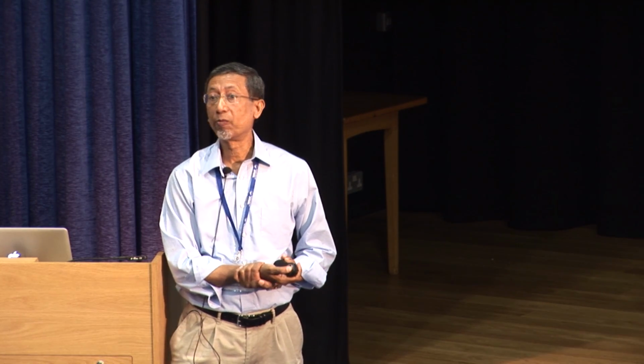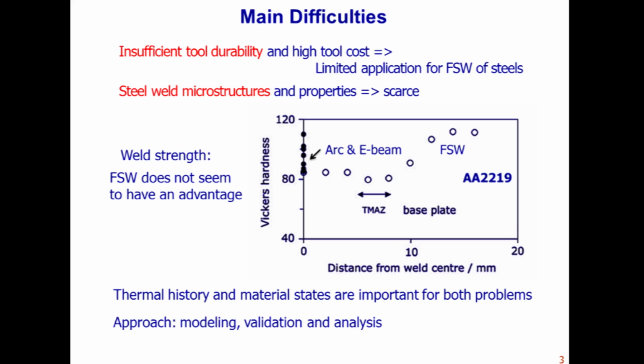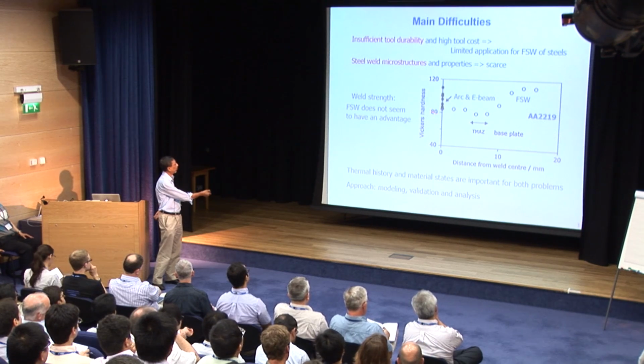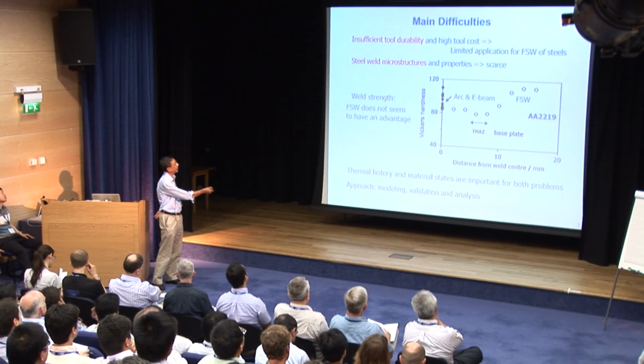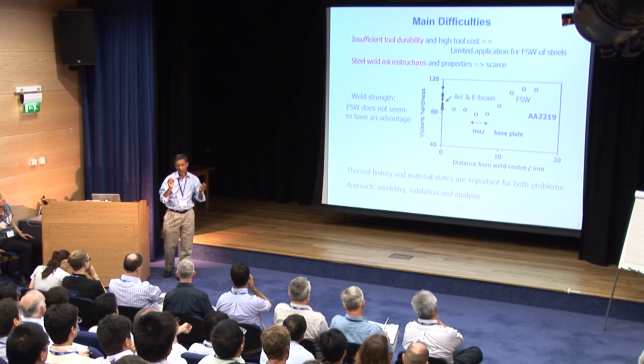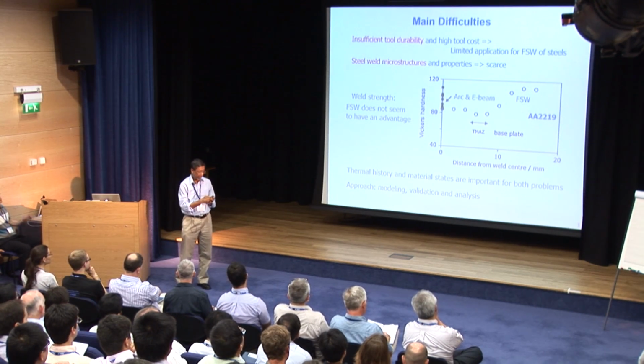And remember that for steels, structure and properties of friction stir welded steels have not been studied adequately. Even for aluminum alloys, the friction stir welding does not seem to have an advantage compared to fusion welding in terms of the strength. And remember, aluminum alloys have been studied a great deal more than steels. So even for that, we cannot get properties always as good as that of the standard plain vanilla fusion welding processes.